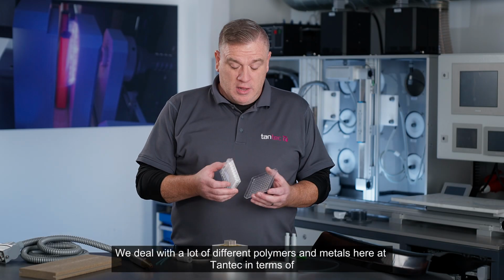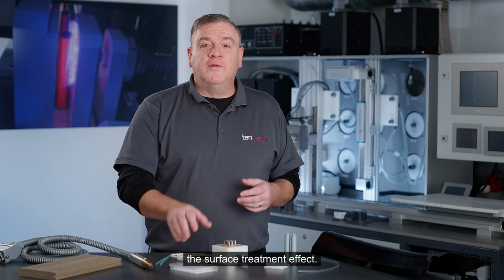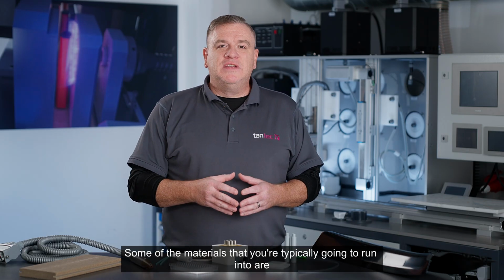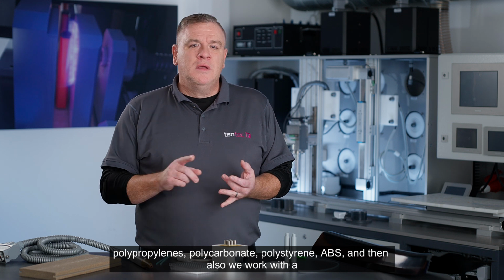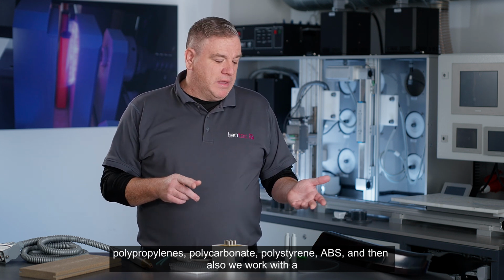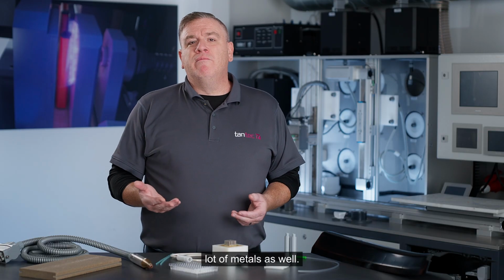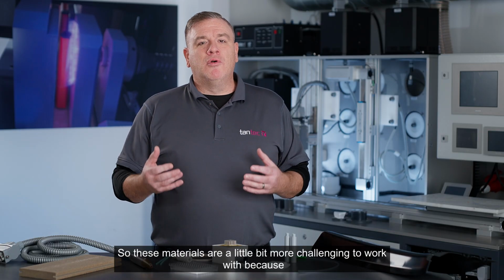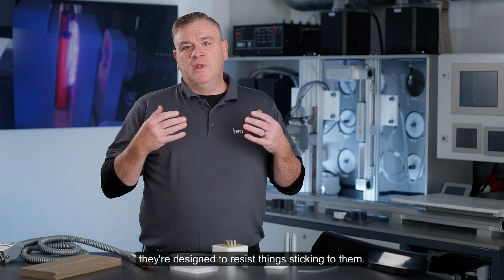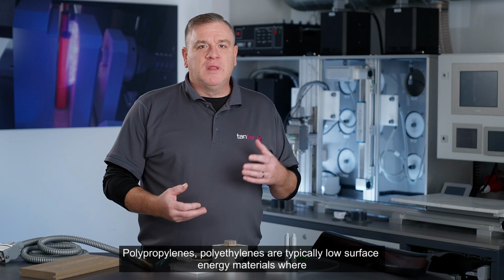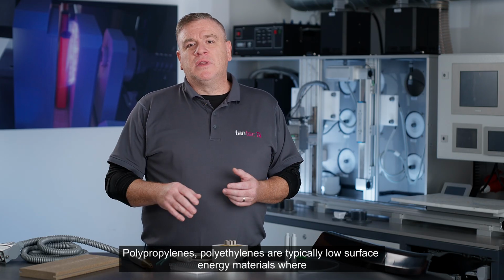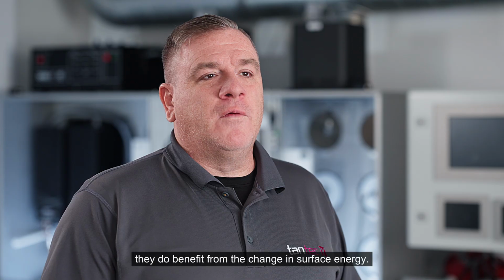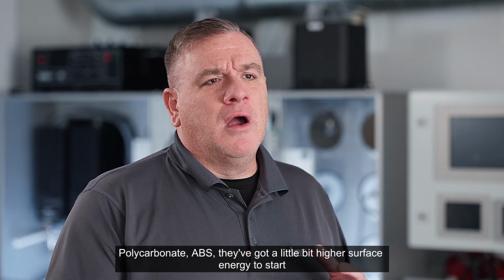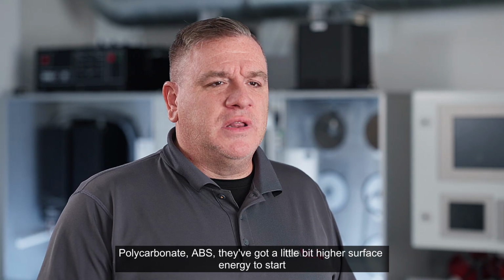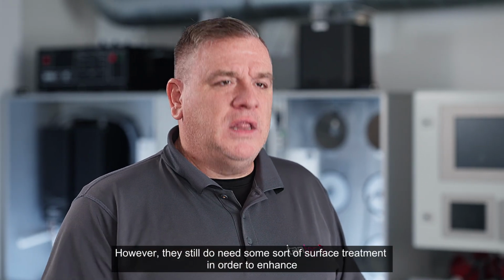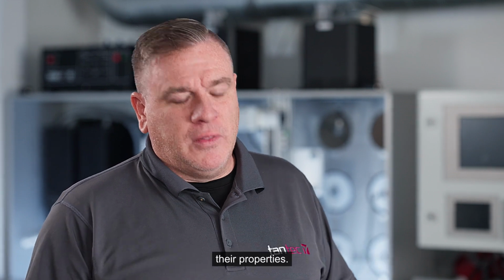We deal with a lot of different polymers and metals here at Tantec in terms of the surface treatment effect. Some of the materials that you're typically going to run into are polypropylenes, polycarbonate, polystyrene, ABS, and then also we work with a lot of metals as well. So these materials are a little bit more challenging to work with because they're designed to resist things sticking to them. Polypropylenes, polyethylenes are typically low surface energy materials where they do benefit from the change in surface energy. Polycarbonate and ABS, they've got a little bit higher surface energy to start with. However, they still do need some sort of surface treatment in order to enhance their properties.